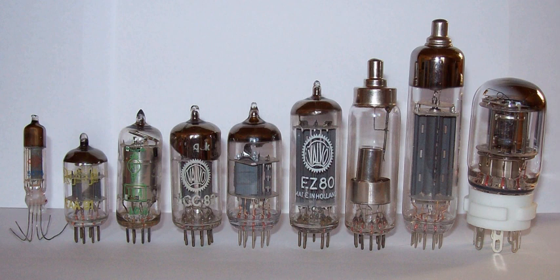Early gettered tubes used phosphorus-based getters, and these tubes are easily identifiable, as the phosphorus leaves a characteristic orange or rainbow deposit on the glass. The use of phosphorus was short-lived and was quickly replaced by the superior barium getters. Unlike the barium getters, the phosphorus did not absorb any further gases once it had fired. Getters act by chemically combining with residual or infiltrating gases, but are unable to counteract non-reactive inert gases.